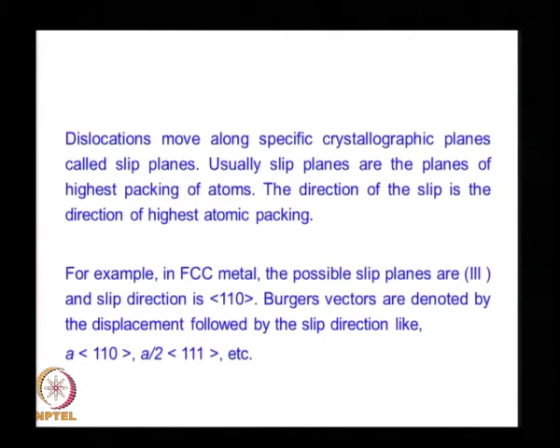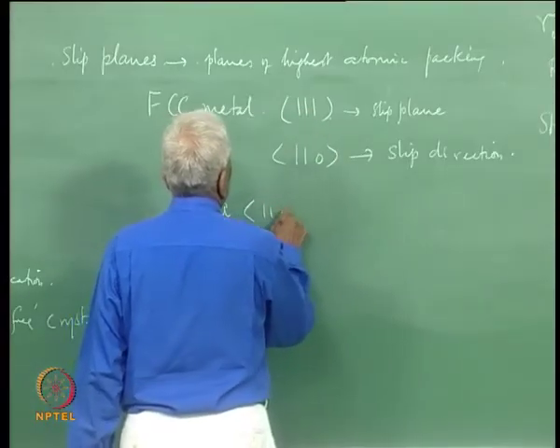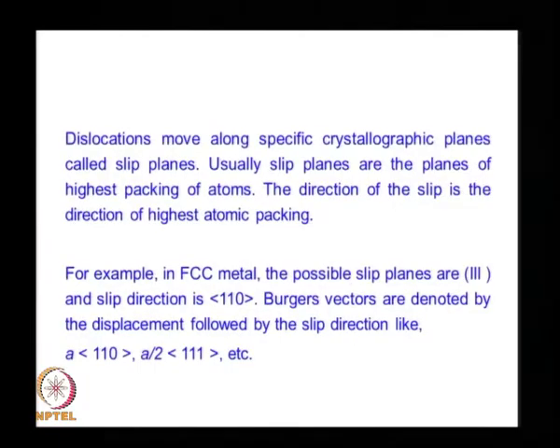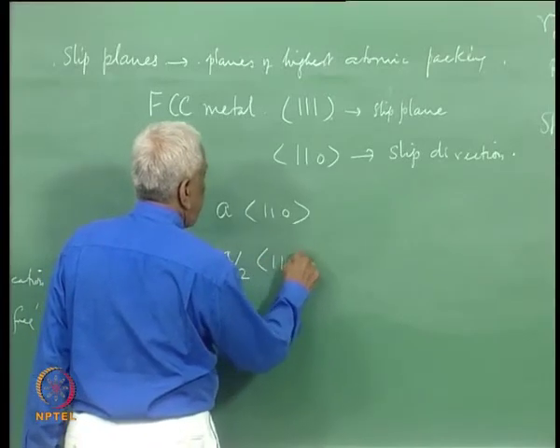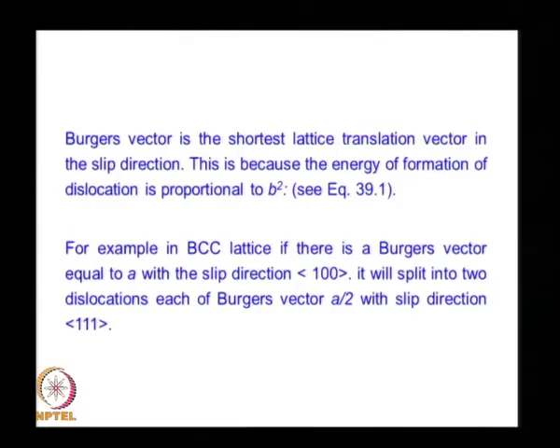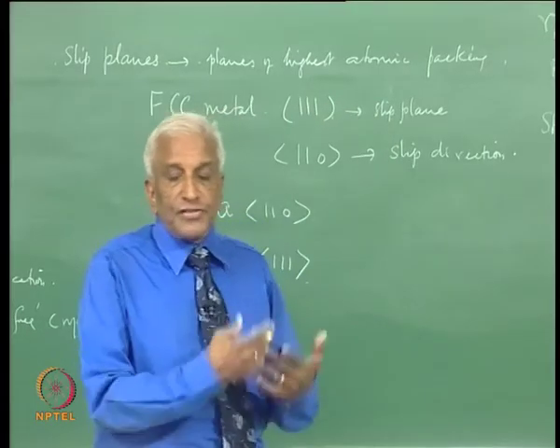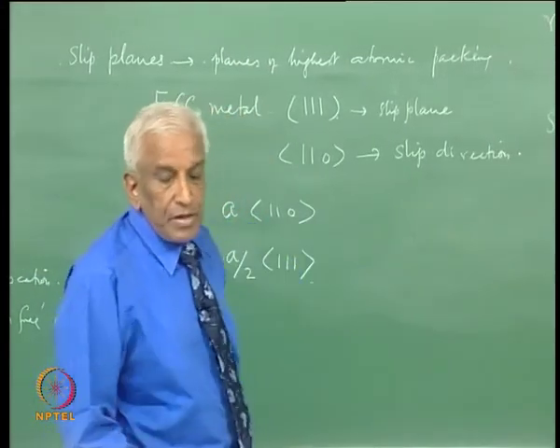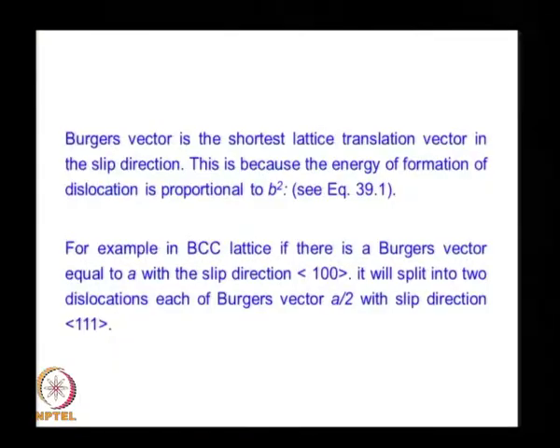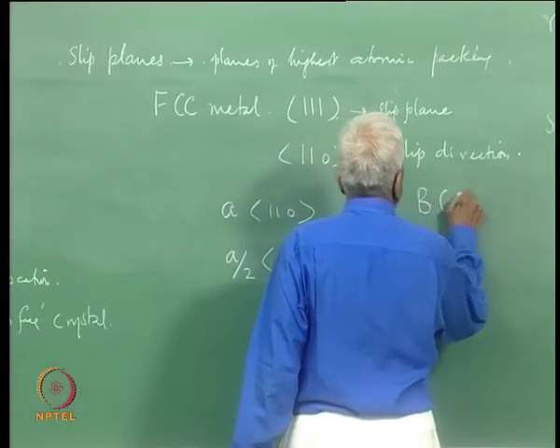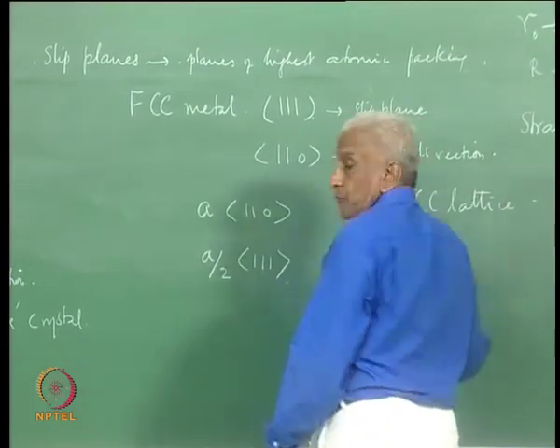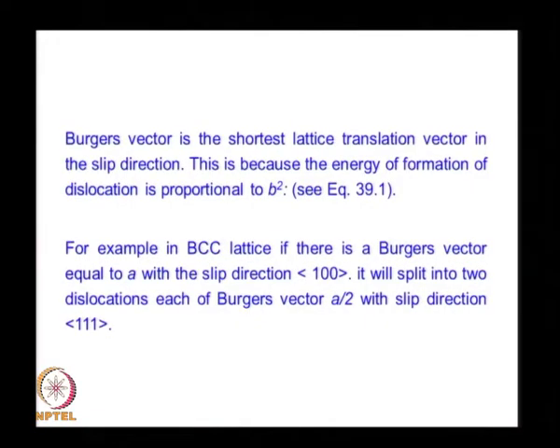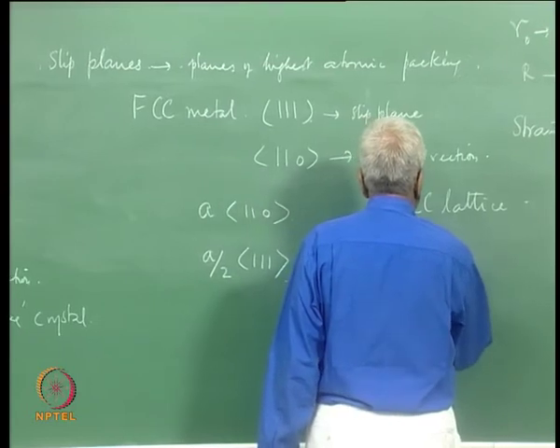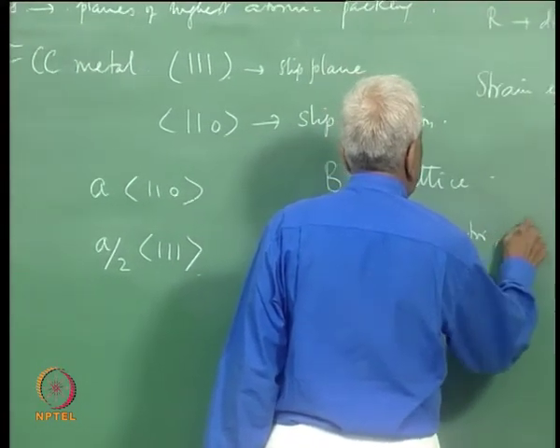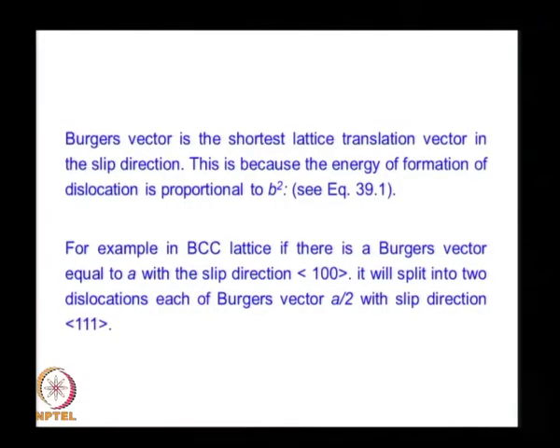So, the Burgers vectors corresponding to this are shown like a<110> or a/2<111>, etcetera. Now, the Burgers vector is the shortest lattice translation vector in the direction of the slip. This is because the energy of formation of the dislocation, as we discussed, is proportional to b square. So, if you have a BCC lattice, if there is a Burgers vector equal to a in the slip direction 100,